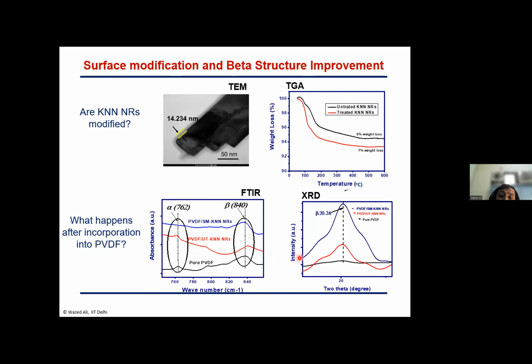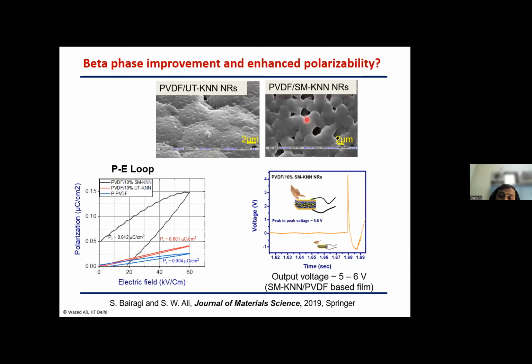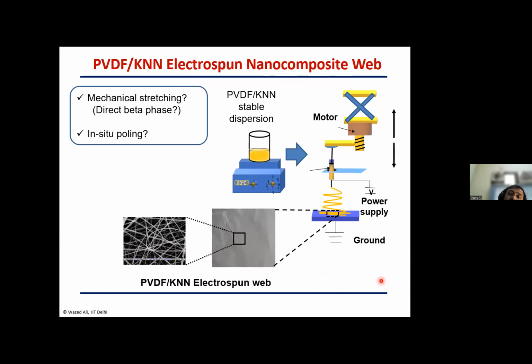And ultimately, we have seen that for this nanocomposite film, when characterized, the voltage we generally got was in the range of 5 to 6 volts. This is in the film form. But if you talk about electrospinning, as I mentioned, we have taken the same combination, that ceramic and PVDF together, and went through the electrospinning process where we are applying high voltage, of course, and in situ poling is happening over here, and that is the main advantage of using electrospinning for production of this kind of device. And also mechanical stretching is happening, right?